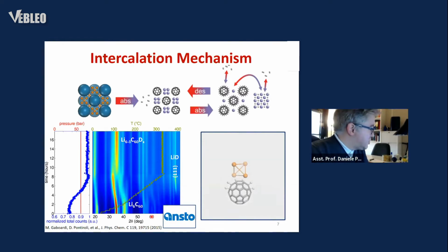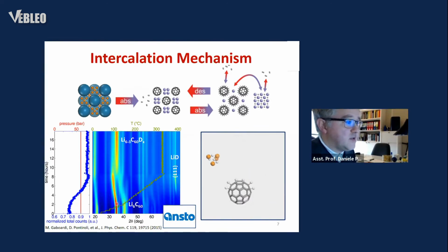The hydrogenation mechanism of these alkali cluster intercalated fullerides has been investigated by means of in situ high flux neutron powder diffraction, which is displayed in this picture for the case of Li6C60. The diffraction patterns collected every minute during the hydrogenation process show the progressive expansion of the fullerene lattice upon heating, indicating the C60 hydrogenation, followed by a side reaction of lithium clusters with hydrogen and the subsequent formation of segregated lithium hydride, in this case lithium deuteride.